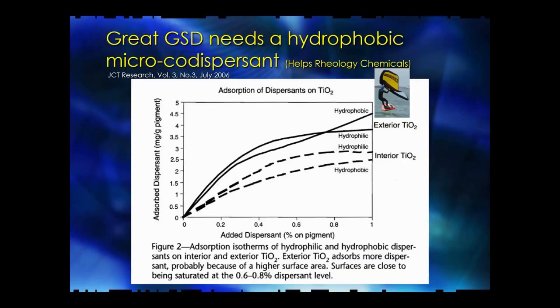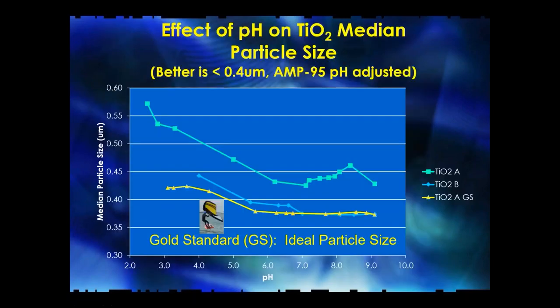So there is one really interesting thing. That exterior TiO2, as you increase the concentration of dispersant, actually has a higher affinity for a hydrophobic dispersant. And you can get a lot of hydrophobic material on an exterior grade TiO2. Why is that? And this is something that I found so interesting, I developed a co-dispersant, what is called a micro co-dispersant. You add it in parts per million to the existing formulations, and you can get super high grind solids. So let's find out what happens when we do add these micro dispersants.